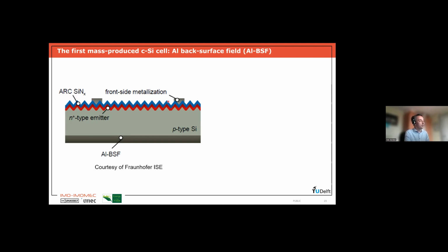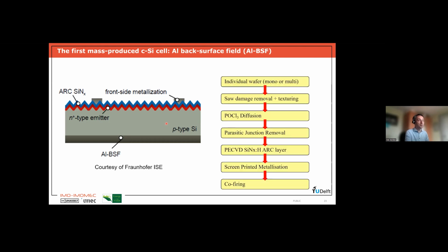And of course, you also have metal contacts, typically silver at the front. And then at the rear, you have as a metal contact aluminium, and you have an aluminium silicon alloy that forms a back surface field. So this feature gives actually the name to the device type, namely aluminium BSF. Now, this is a relatively simple cell structure, but still you can reach relatively high efficiencies with it. So it was for many years very successful in the industry, especially because it's also very easy to process. You don't need a lot of process steps, which makes it, of course, very interesting for industry to mass produce.